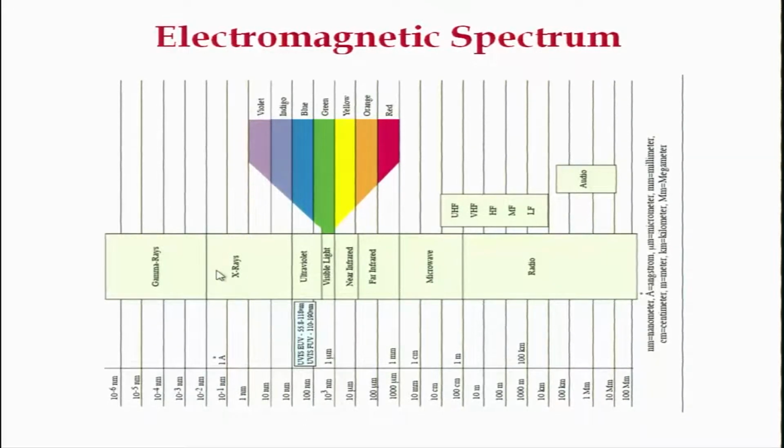So, that is where we bump into X-rays, and these X-rays, the ones on the left, with wavelengths of the order of 1 angstrom to 2 angstrom, are useful for us. You can have X-rays of 1 nanometer wavelength as well, but that is not useful because most materials have lattice parameters which are far smaller than 1 nanometer.